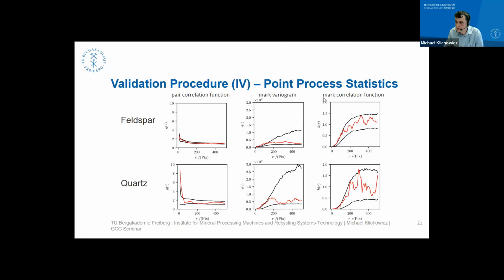And the last measure is the mark correlation function. It characterizes the size of the marks as a function of the interpoint distance. That is, we have small values for small marks, and bigger values for bigger marks. And here we see that for small distances, we have very small marks, which means that we have smaller grains at smaller distances.